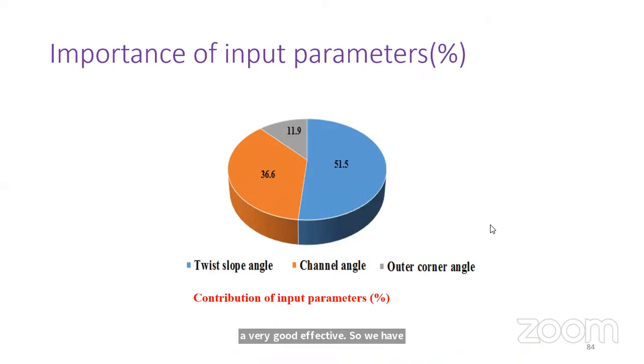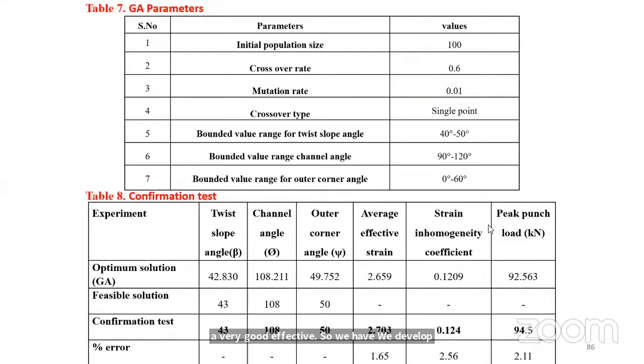Then we have gone for various optimization processes like ANN and GA in order to find the optimum parameters to design the die. With the experiment on the twist slope angle, we can get an optimal solution of 42 degrees, channel angle of 108 and outer corner angle 49. With these three parameters, we have got an average effective strain of 2.659, strain inhomogeneity of 0.1209, and the lowest peak punch load of 92.563.